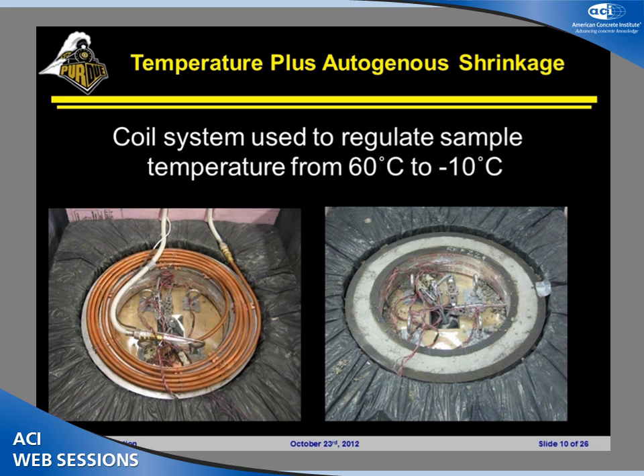So in addition to using the rings just to monitor drying shrinkage or just to monitor autogenous shrinkage, what we're actually going to do is we're going to use a test here where we're going to restrain the concrete, and then we're going to also try to send the concrete through different temperature cycles. And what we're really looking at here is sort of a twofold issue. One, if we drop the temperature, we can see how much residual stress capacity there is in the system, how much we have to drop the temperature to make it crack.